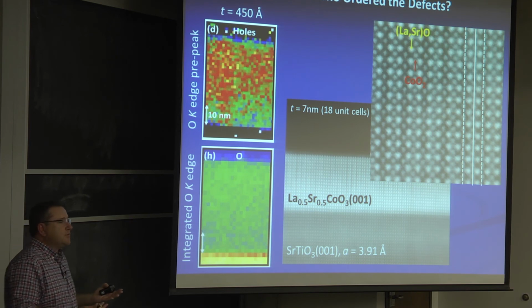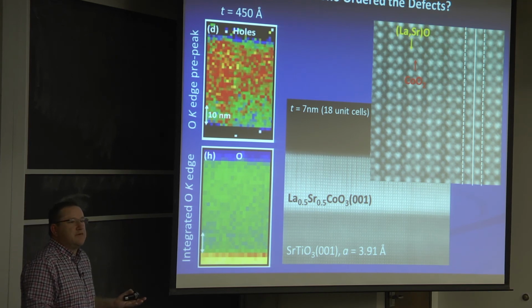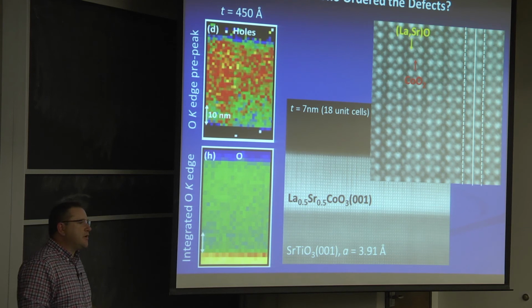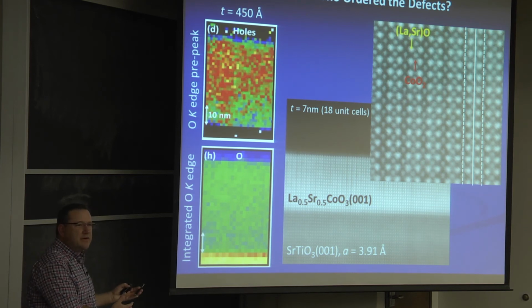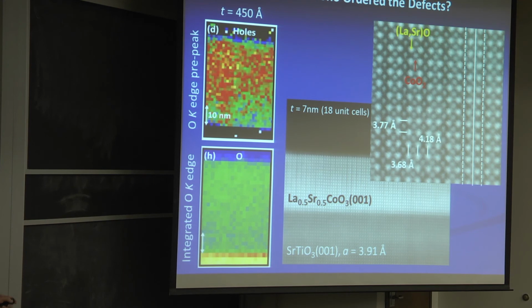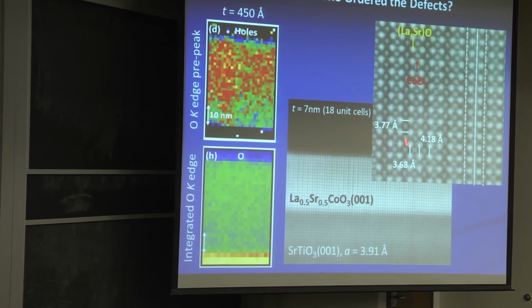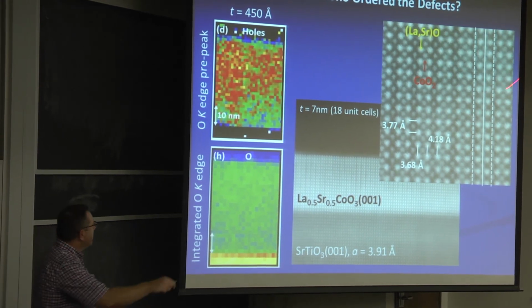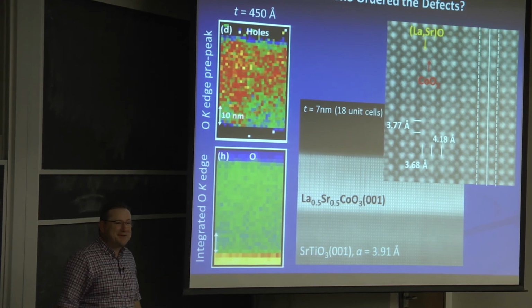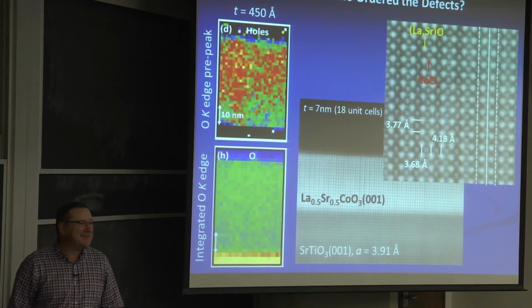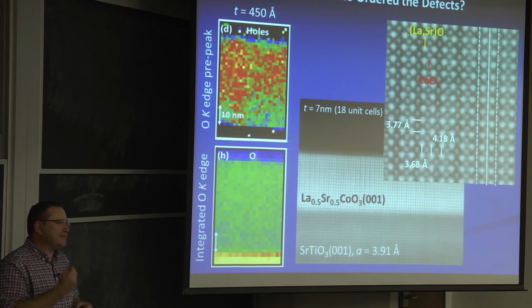And the question, of course, was, why do they do this thing? It's oxygen vacancy ordering. We can find some obscure compounds where oxygen vacancy ordering happens, but it shouldn't happen in this material, and we found it was there, and it's only there at the interface, right? And I can tell you, this was very exciting for me. I was on an airplane. I did not have my computer. I had a big piece of paper with this printed out, and I had a ruler and a pencil. And I was doing all sorts of stuff with interplanar spacing.